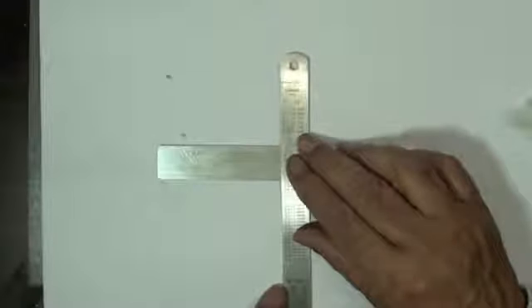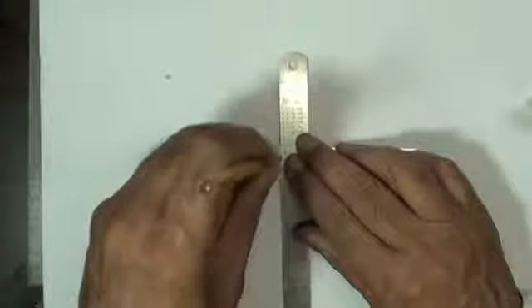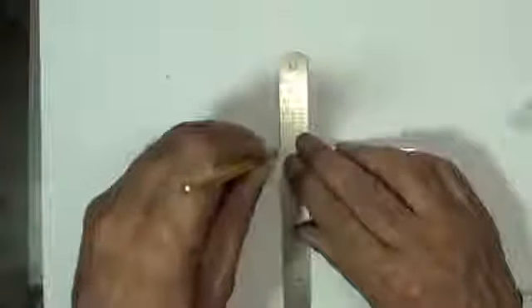The pencil will actually flatten some of the peaks that we created through the sanding process without changing the thickness of the aluminum beam. So he's going to go back and forth a few times there and produce a pencil mark on the surface. It depends on the material that you're bonding the gauge to, but VJ, what would you recommend for steel, if you were working on a harder material? Well, if it's a hard material which cannot be marked with a pencil, then we can use a ballpoint pen. Excellent. Which has a nice round ball in the front. That will not create a scribed mark, but it will burnish the surface and create the same effect, so that the mark is very visible under proper light conditions, and allows us to align the strain gauge properly on the beam. Excellent advice.